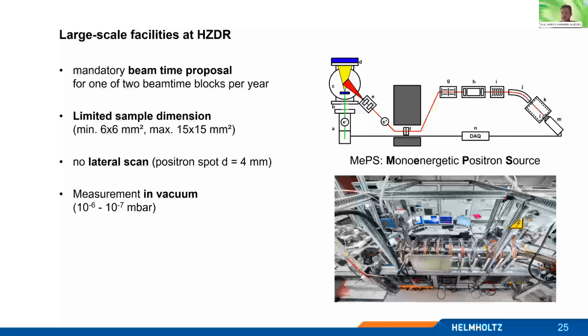Another limitation is the sample size. So the sample should, in the best case, be 10 times 10 millimeters, so it fits properly to our sample holder, and there is no lateral scan because the beam spot is approximately 4 millimeters and not larger or smaller. So be aware of this. But as I said, the implantation energy can be varied, and therefore depth profiling can be done with this machine. And in addition, your samples should be vacuum stable.